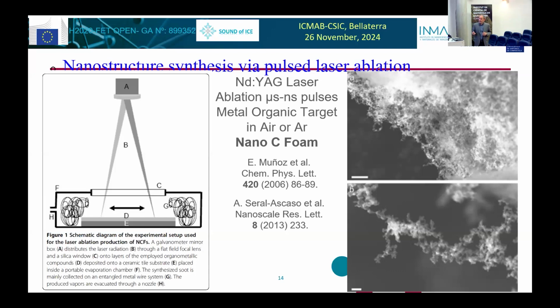And so we did that for many years, we started to use organometallic compounds and ligands already without metals. We found out just the use of the ligands without the metal was enough to get the same structures. So the metal did not have really a significant effect on the nanostructure preparation.